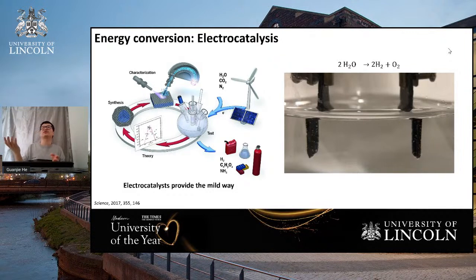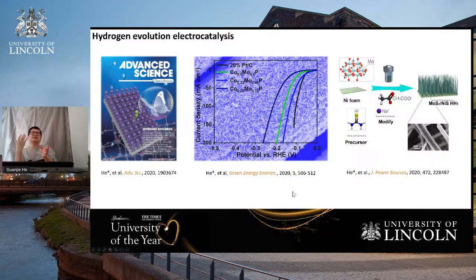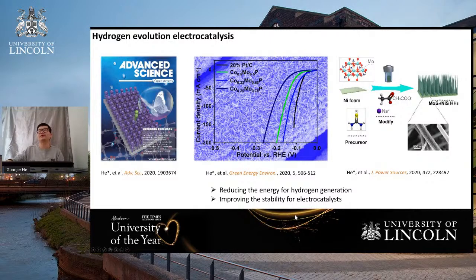So there's a question related to that. Can we use less electricity to generate more hydrogen? This is what needs to be done in the electrocatalyst design. And our group has rich experience in developing different hydrogen evolution electrocatalysts. We try to boost the active sites, we try to boost the surface area, or we call it the electrochemical surface area, and try to increase electronic conductivity for our electrode design. We need to reduce the energy needed for the hydrogen generation. And we also need to think over how we can increase the stability of such electrocatalysts.